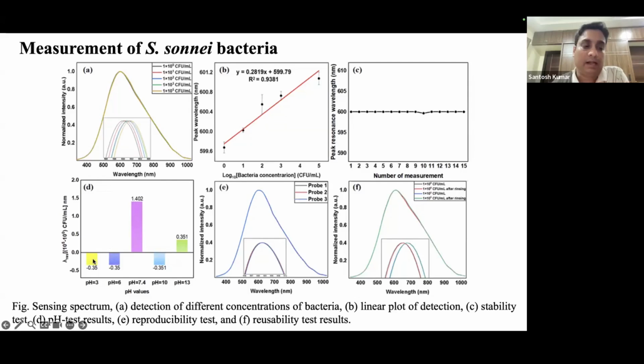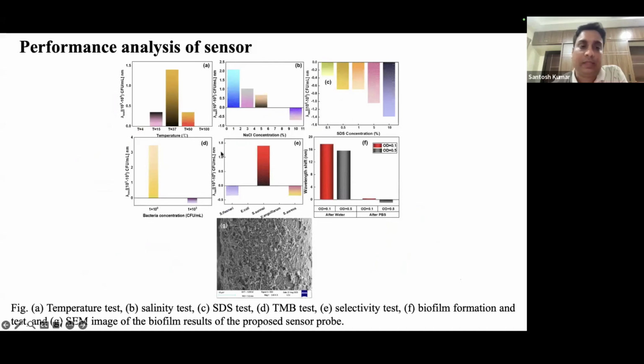And we have also prepared higher and lower concentrations of the bacteria in different pH solutions, and we found that the sensor works better at 7.4 pH, which is equivalent to serum. So we can say that this can be useful for serum detection or in healthcare applications also. Later on we have done the reproducibility test and reusability test, and that is also quite good. Then we have done the temperature test with different temperature solutions, and we found that at 37 degrees the bacteria is alive and working, and we get the maximum wavelength shift.